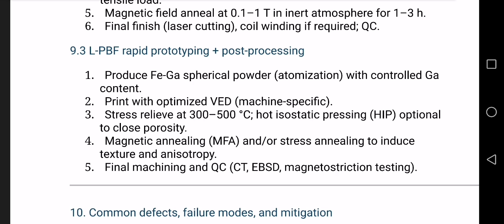Okay, last point, common defects. LPBF prototyping and post processing. Its steps are: produce spherical powder first. Second, print with optimized energy density. Number 3, stress relieve at 300 to 500 degrees Celsius. Number 4, HIP if needed. Number 5, magnetic and stress annealing. Number 6, final QC, CT, EBSD, magnetostriction.